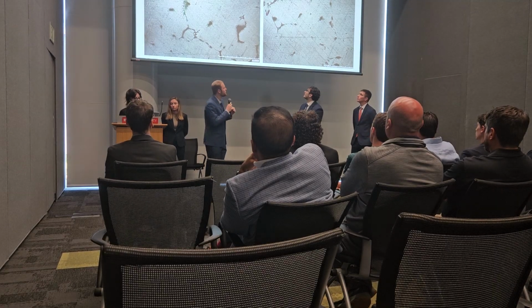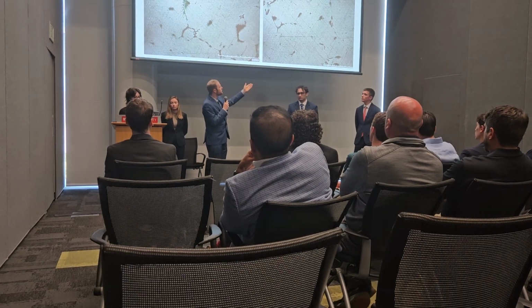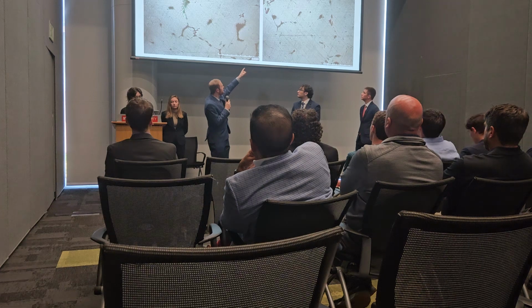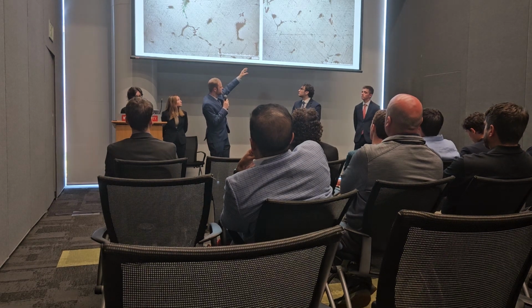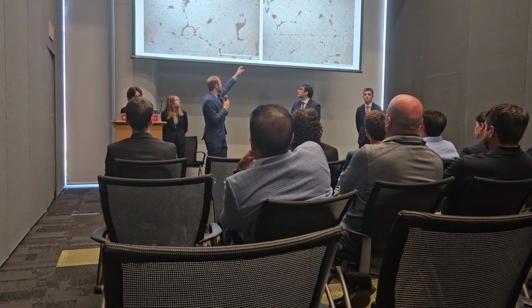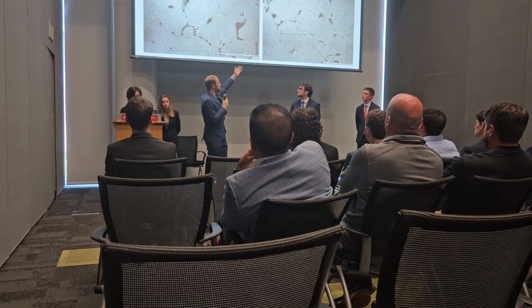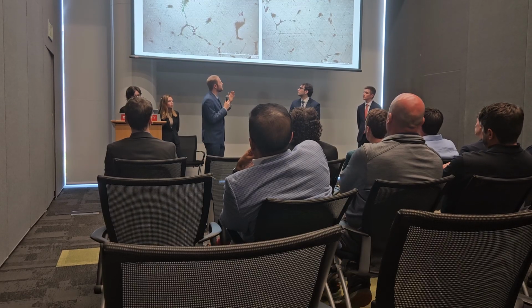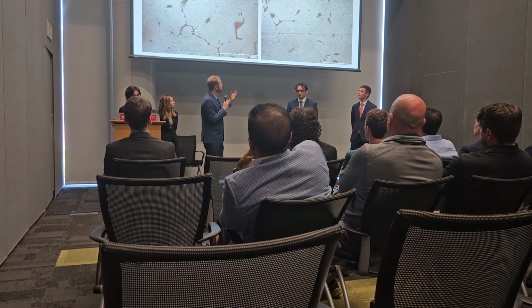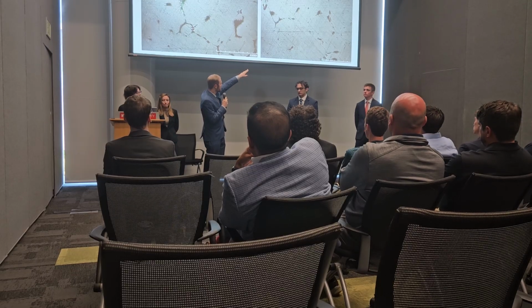But from this, we were able to do analysis on the microstructures. As you can see above, the grains form around these little air pockets. The porosity, these little black spots, are air pockets. The porosity is due to the lack of a vacuum chamber, which would have pulled these out. But you can also see these little pink dots.